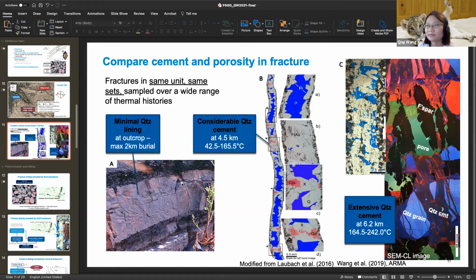So, if that answers your question, and in the subsurface, obviously, if we know where the cores are from, at what depths, and we measure the temperature within the bridges, we know the fluid conditions, like the temperature and the composition of the fluid, when the fracture was forming, or at least when the fluid flowed through the fracture when it was still active and open. So with that, I would say we are able to identify when the fractures formed.